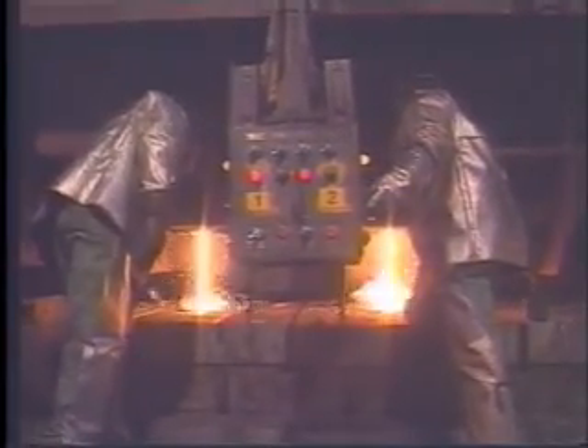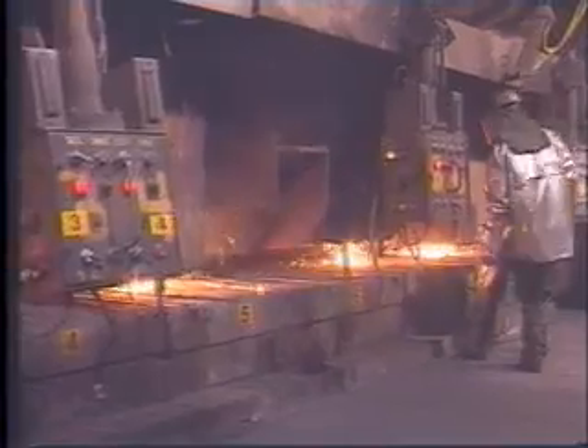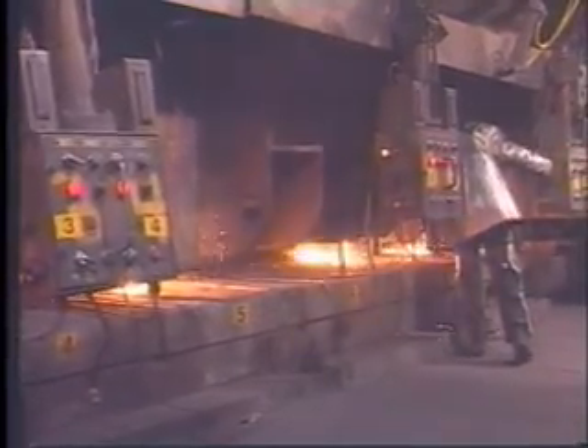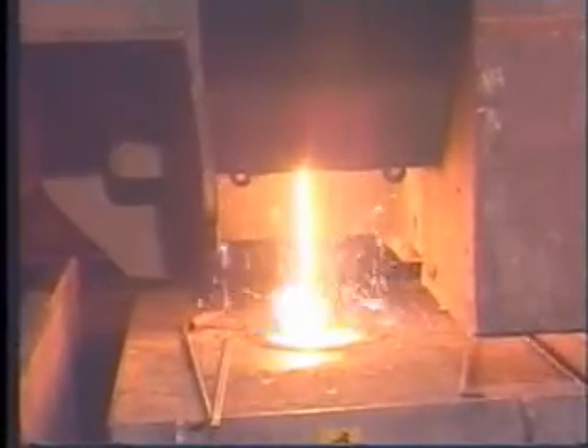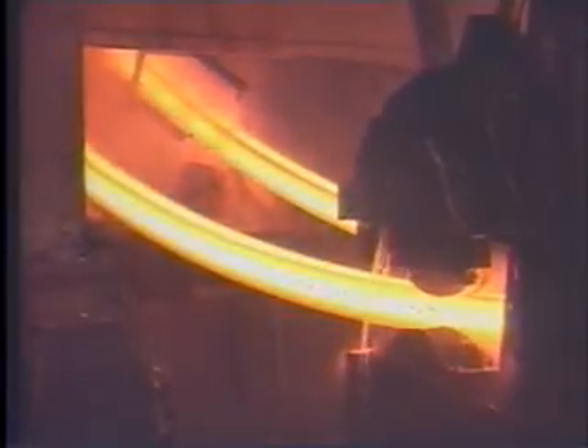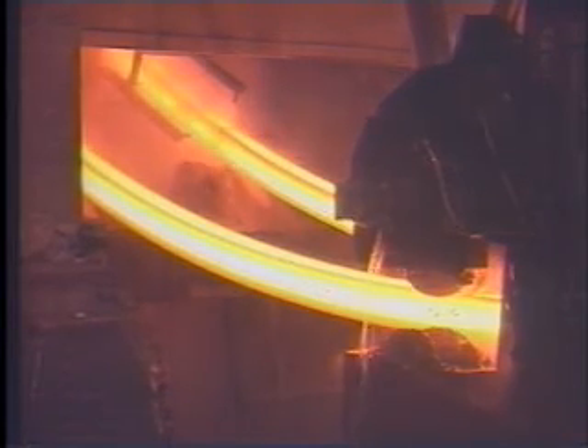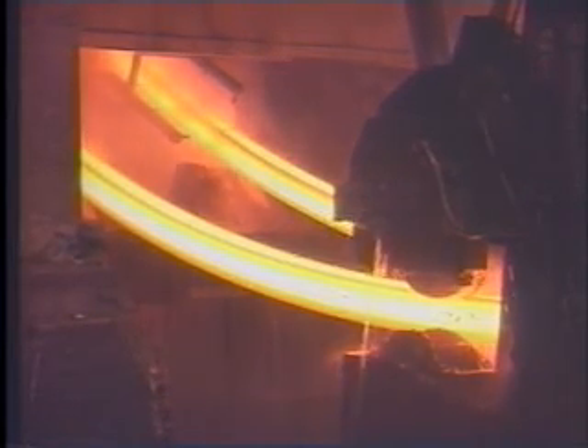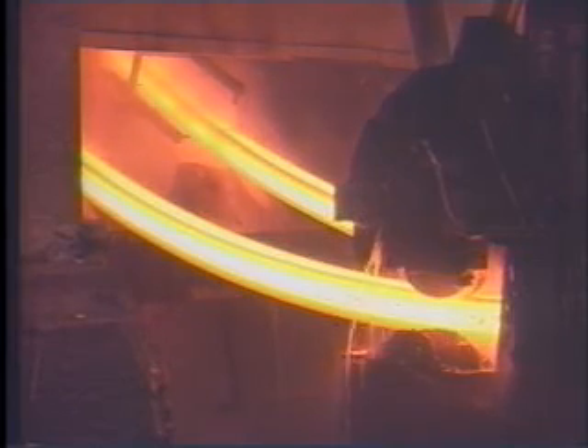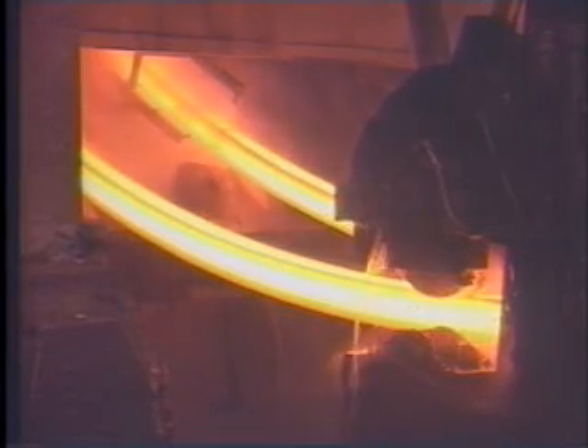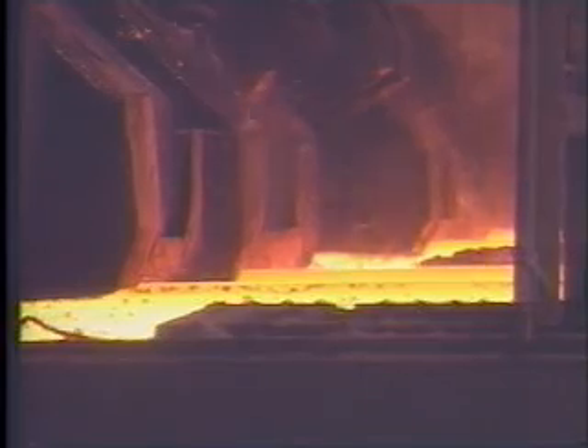Steel flows from the bottom of the tundish from 8 separate streams into a water-cooled mold, which is 5 1/8 inch square. This mold is used to solidify the skin. As more steel is poured into the mold, a continuous length of solidifying steel is pulled from the underside of the mold. As the section exits the mold, it's cooled with sprayed water until it is completely solidified.